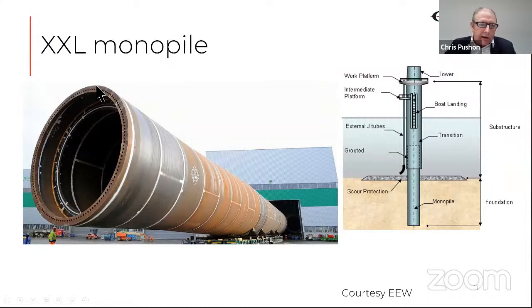One of the very critical areas is where you attach the tower attachment flange by means of a full penetration weld. Typically, this is over 100 millimeters in thickness. So 100 millimeter full penetration welds all the way along. And productivity is a real key to success in the economics of offshore wind.